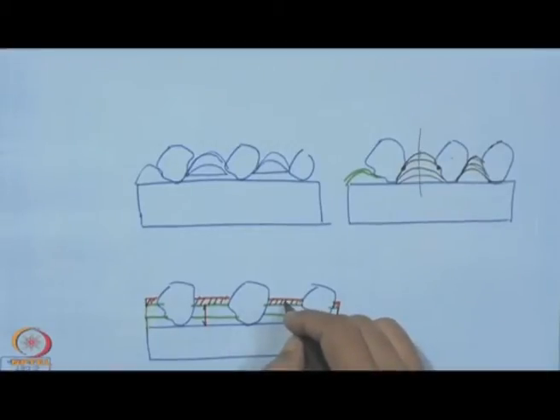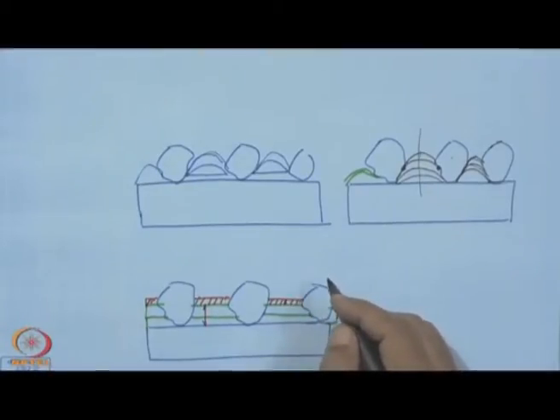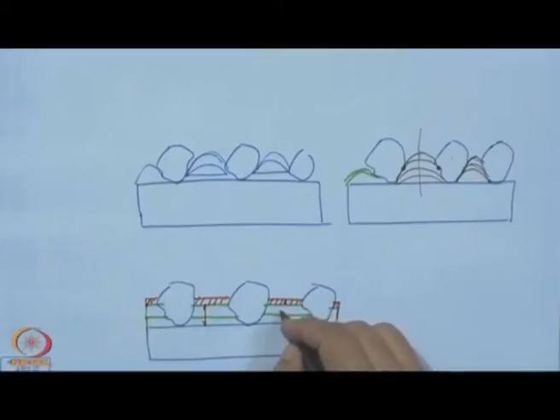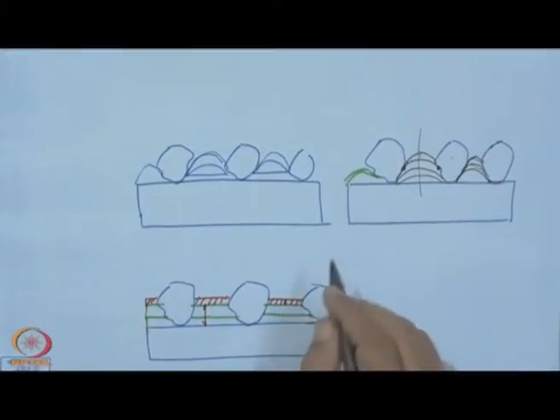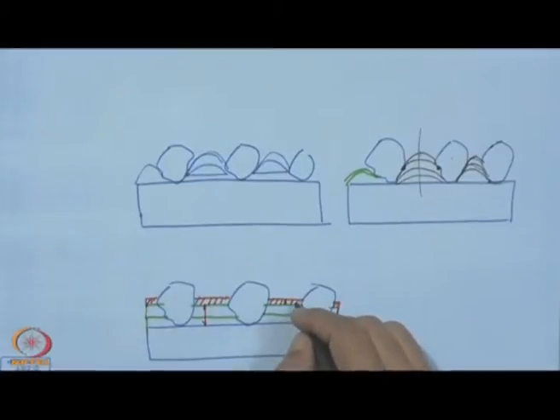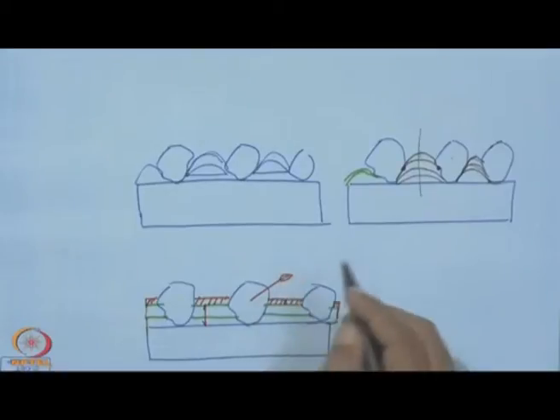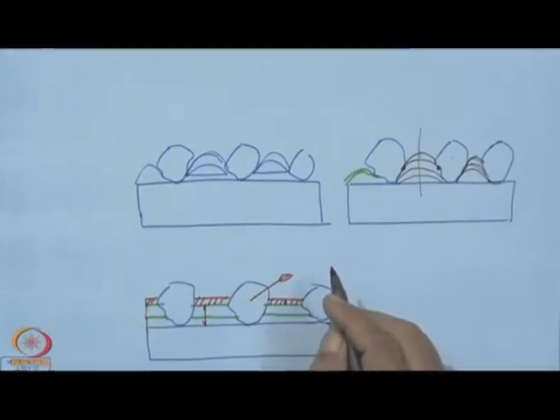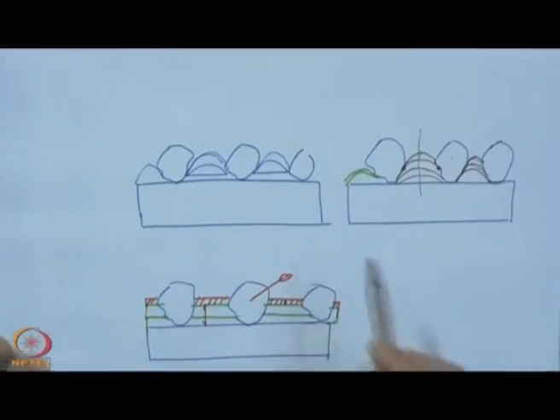So, that will give some kind of wear resistance in this case, because of the simple reason that during grinding there can be erosion of this material, and if it is too soft, in that case this material will wear out, leaving no material support, and there can be undesirable fallout of the grit.